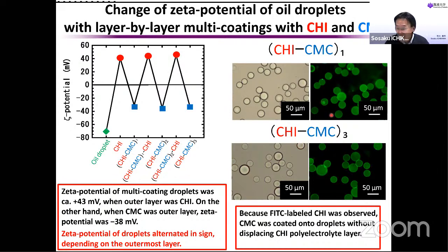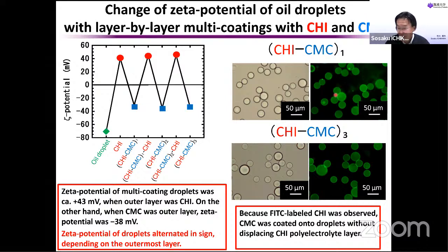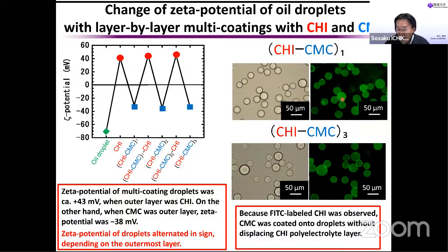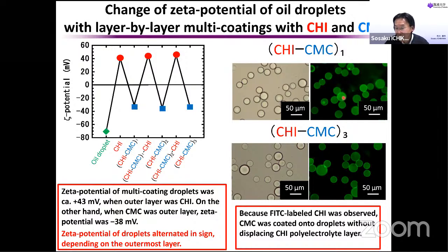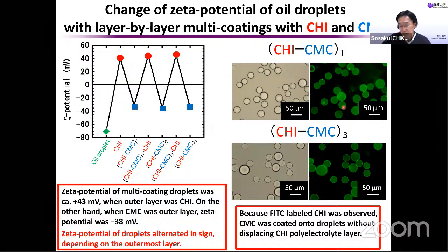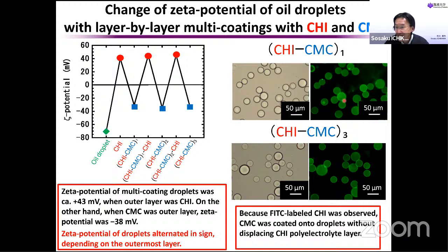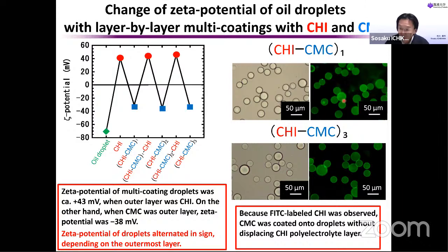Then this is a microscope image of the oil droplet, and this is a fluorescence image of the oil droplet. We use a fluorescent label on the chitosan. So you can see the green fluorescence on the oil droplets like this. All of the oil droplets have green fluorescence. It means that the surface of the oil droplet is covered by fluorescent chitosan. So it's one piece of evidence of the surface coating of the oil droplet.